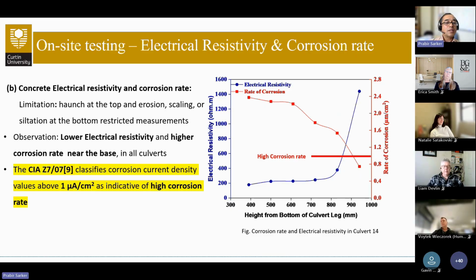Electrical resistivity and corrosion rate were plotted along the culvert legs. The limitation was that at the top of the leg there is a haunch, and at the bottom there was usually scaling, siltation, or some erosion, so that part had to be excluded.